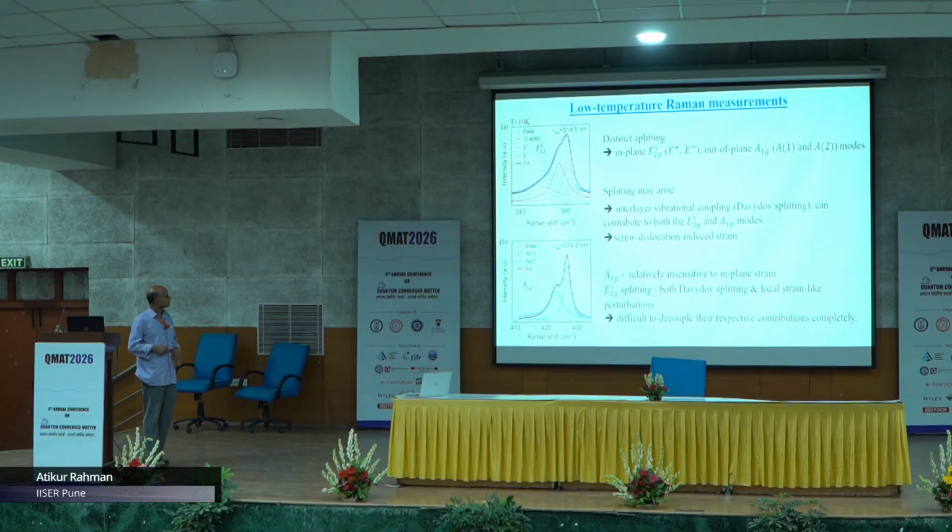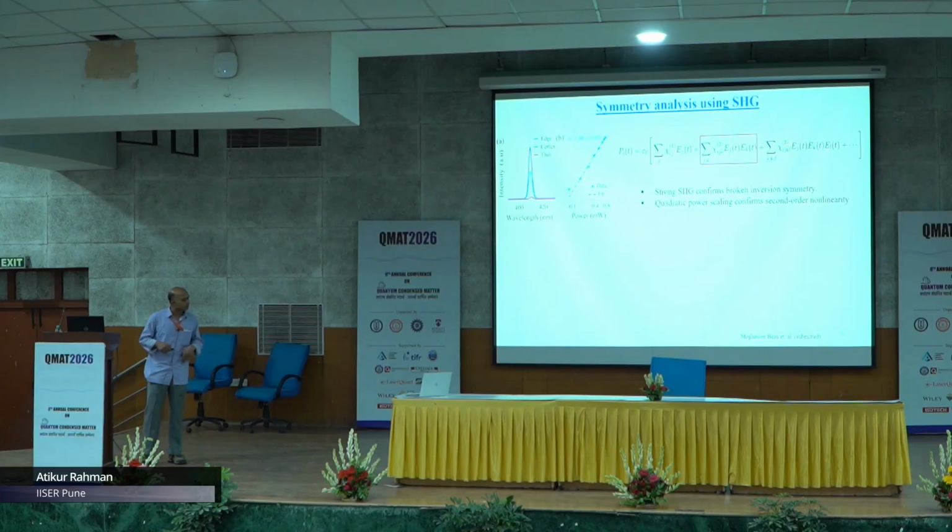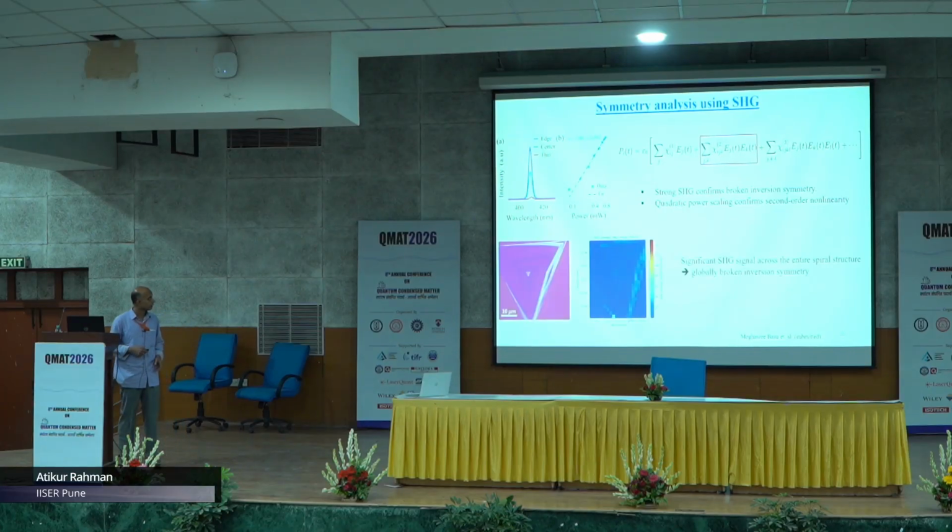So then we moved to the next experiment. We did the second harmonic analysis of this sample. We did a thorough measurement, again in collaboration with one of our collaborators in Poland. What we found is that with increasing thickness, the signal is increasing. Basically, there is a constructive interference that is increasing the intensity of the second harmonic signal. And if you increase the power, you see an almost quadratic dependence, which says that yes, second-order nonlinearity is there. Somehow this video is not working.